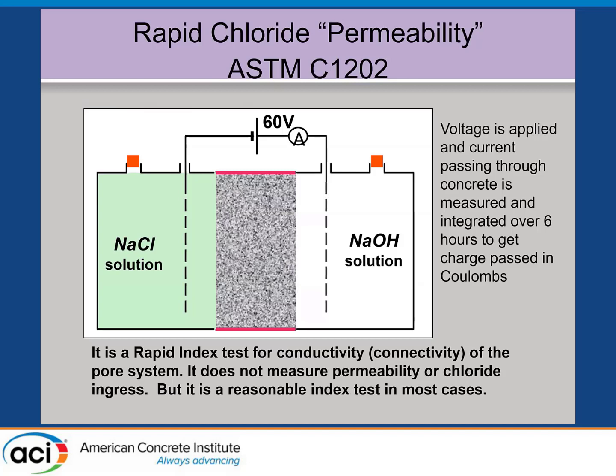1202 has been around since the early 80s, developed by Dave Whiting at the PCA many years ago. And it's really an awkward conductivity test. It's a rapid index test that measures the conductivity of the concrete. You saturate the concrete, you put it between 2 conductive solutions, you apply a voltage, you measure the current flow, and you multiply that current over the 6-hour time frame to get coulombs, which is the charge passed over the 6 hours. And there's people who complained about that test method. But in general, it has worked. I think if Dave Whiting was alive today, he wouldn't pick that test method now because things have evolved over the last almost 40 years.